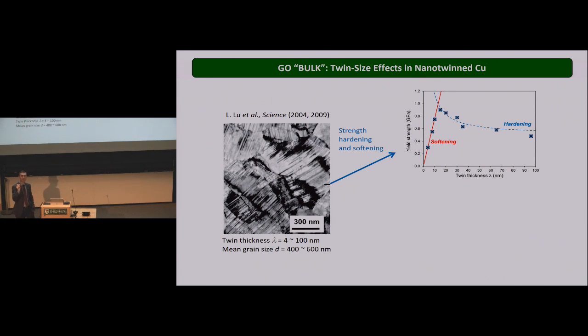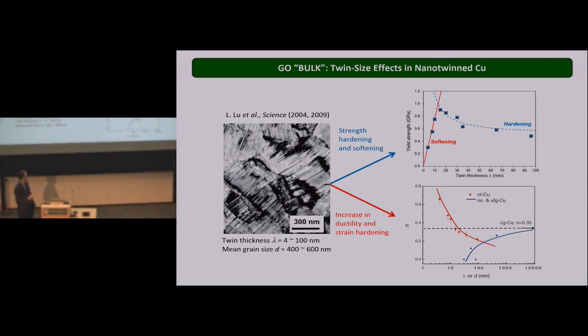Okay, but this is just about the strength here. Another thing that's very characteristic about nanotwin metals is this. Imagine you make a metal by simply reducing the grain size. You'll find that this metal will have an increased strength. It's a Hall-Petch effect. But at the same time, the ductility drops dramatically. This is the behavior you find in this blue curve here. When you decrease the grain size D, the ductility drops dramatically. So basically, it's a high strength but more brittle material. And for engineering application, that's not great.